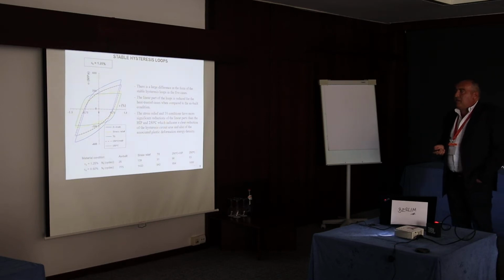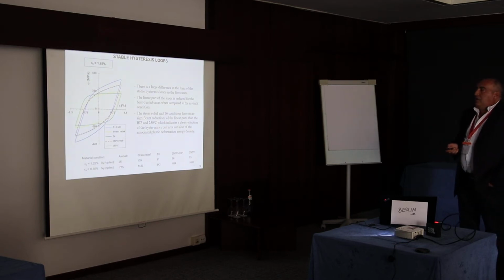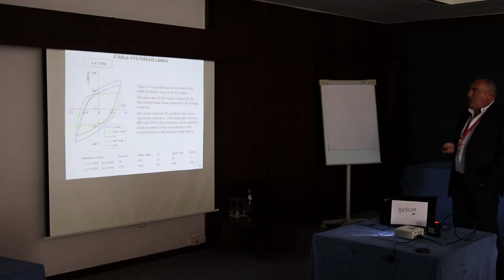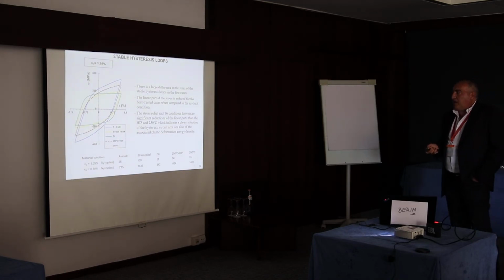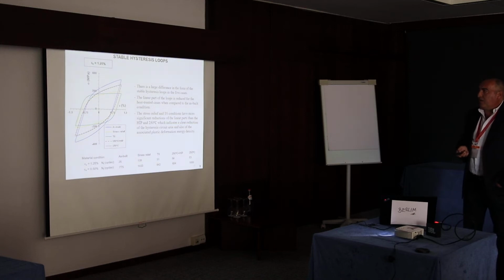When we compare the stable stress loops at midlife for all the 5 cases, also for a strain amplitude of 1.25, the same for lower stress amplitudes, it delivers a large difference in the form of the stable stress loops in these cases. The linear part of the loops is reduced, as already said, and the stress relief and T6 conditions have more significant reductions of the linear part than the HIP and the 215 degrees treatment, which indicates a clear reduction of the hysteresis loop area and also of the associated plastic deformation energy density that we'll see later on, exposed in the graph.